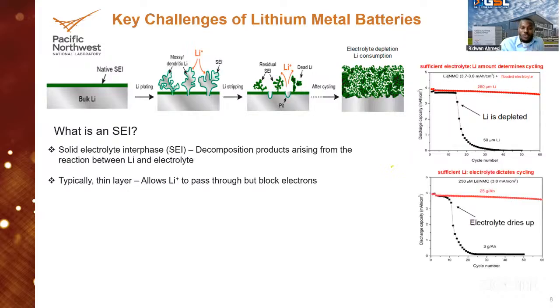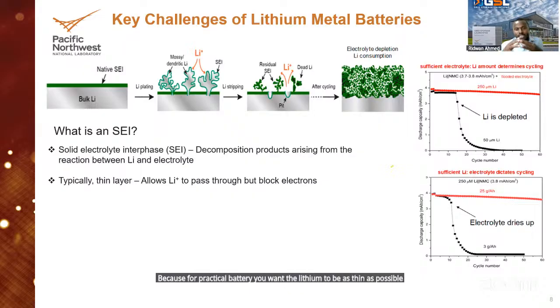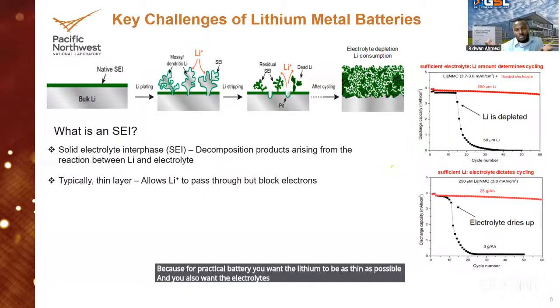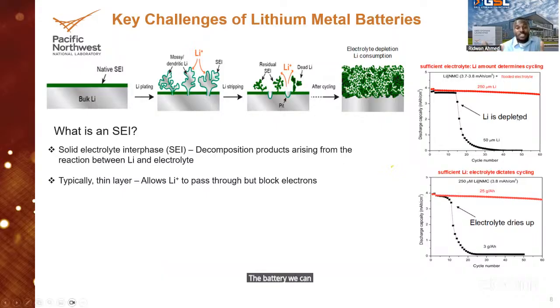And the same thing goes with if you use a very lean electrolyte, because for practical batteries, you want the lithium to be as thin as possible, and you also want the electrolyte not to be much. You want lean electrolyte. So if you're using those two for practical batteries, the battery can easily fail. That's basically what we're trying to show with these graphs.